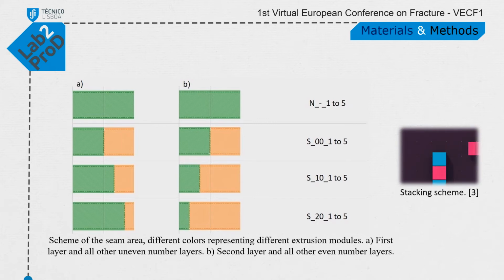On the seam area, the contour of the part is generated with the negative offset of the part's boundary and then cut by the seam line. The infill is generated for each area with an intersection with a set of equally spaced lines. Therefore, the intersection in each layer is achieved by intersecting contours over contours and infill over infill, like it was with a single extruder. During manufacturing, each layer alternates between figure A and figure B.